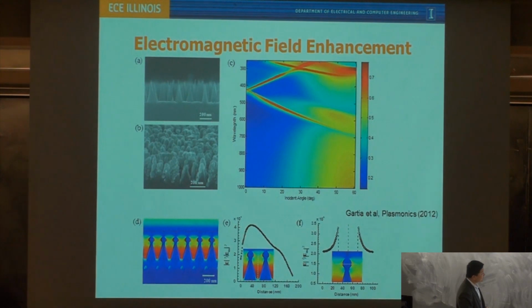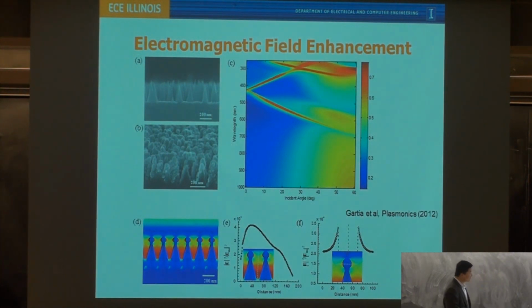What we want to have basically is a substrate can give us a EM field enhancement at very large, very broad bandwidth. So if you start with a highly ordered structure like this, if you run a simulation and you find out they only have high enhancement at some particular wavelengths or frequency, sometimes it's not very convenient for us to do experiments because in that case you really have to find a fluorophore or fluorescent protein has exactly matched resonance frequency with your substrate. So instead of doing this highly uniform way, okay, by the way here you can see if you really control the structure well, you can even get your electric field intensity enhancement for more than 40,000 times.